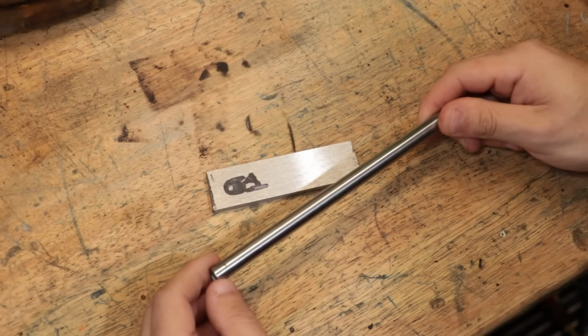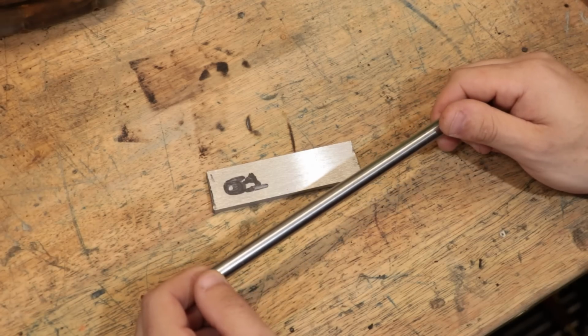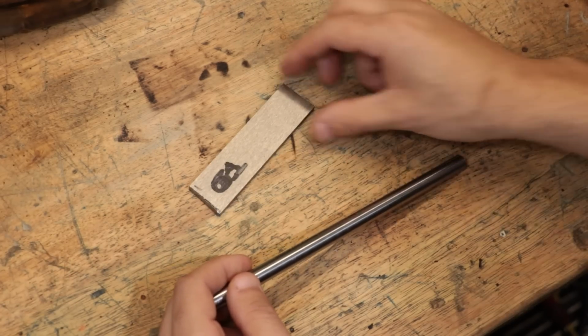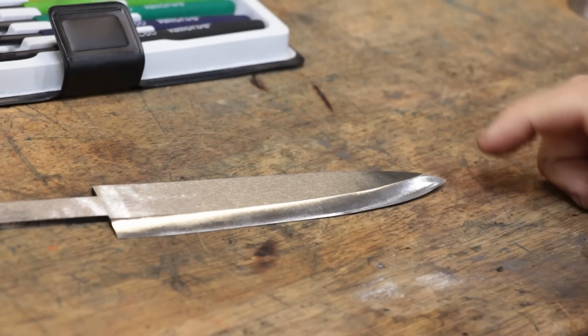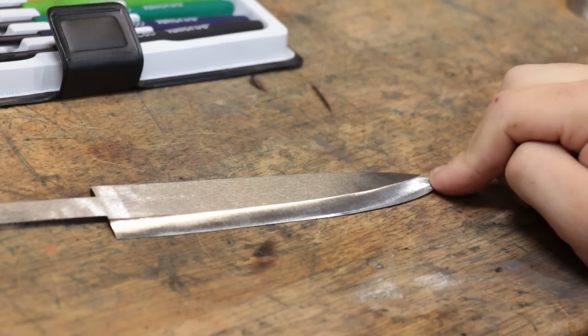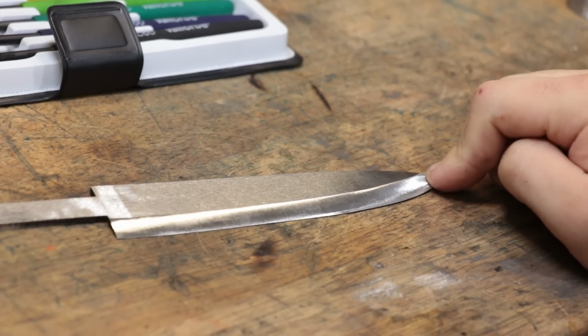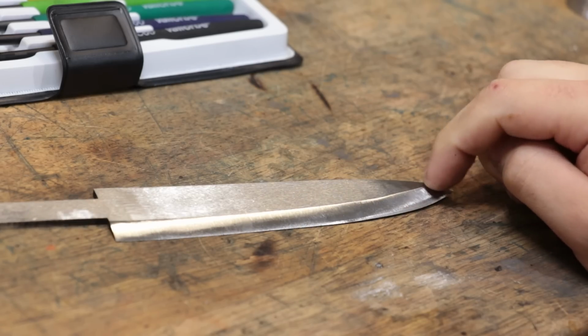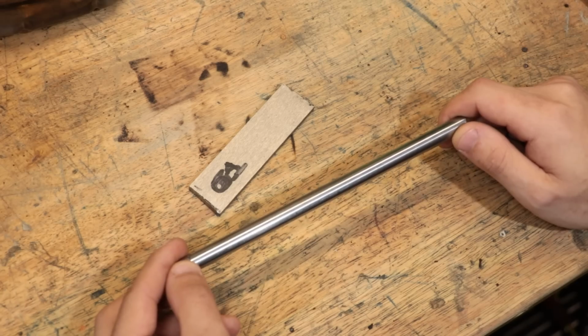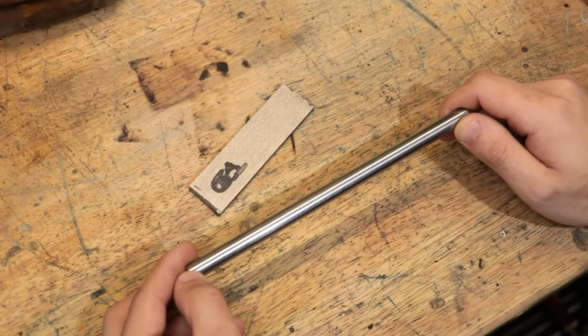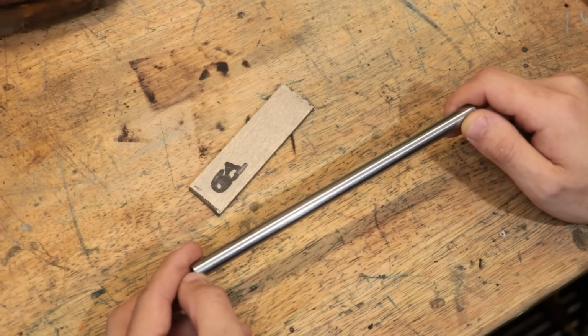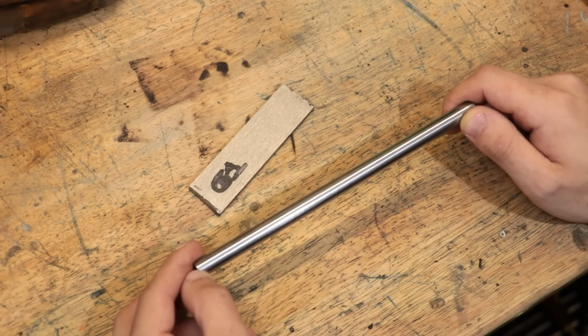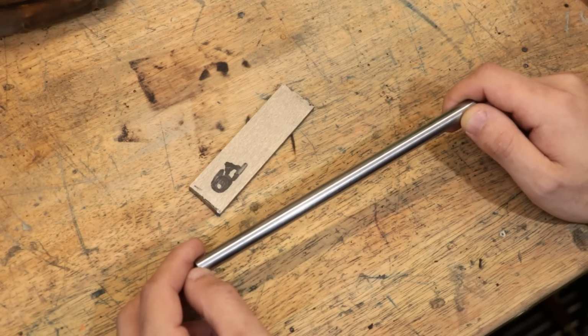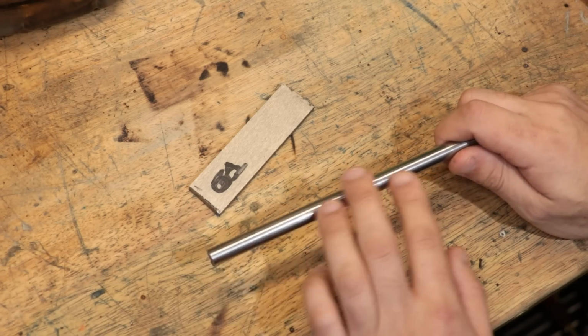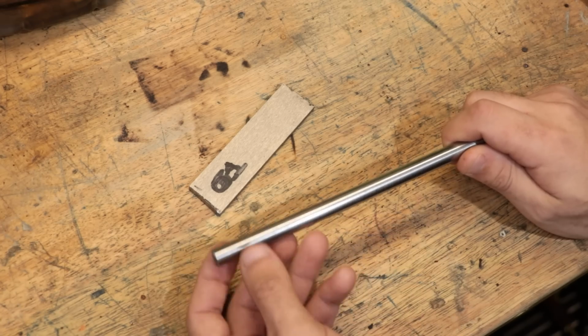Now, the big advantage to having these high hardenability steels is that if regular room temperature oil is still too much of a thermal shock, like it was when I made the knife a few weeks back, it means I should be able to quench it in hot oil, say between 150 to 200 degrees Celsius, while still being able to form that high hardness. The big advantage to this, obviously, is the thermal shock is going to be less because the rate of cooling is going to be reduced, but we still have all that time available to form that martensite.